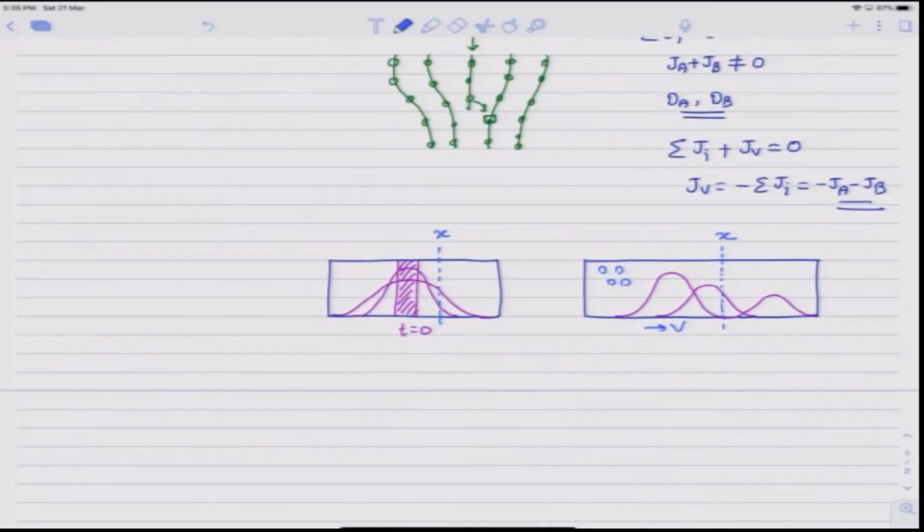Then it should not react with water. That means it should not dissolve, or it should not have any chemical reaction with water. Otherwise, we will lose the chips and we won't be able to track. In the same fashion, we need a marker which can stick to the lattice plane and which is stable at the diffusion temperature, which means the marker should not diffuse in the matrix, and also it should not react with the matrix or with the other diffusing elements.